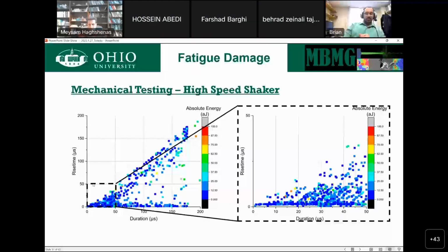And that means all of those waves for a fracture type event should exist down in this low rise time, low duration area. As you move away from that, you can start to introduce other mechanisms: more of a growth response, a longer crack increment, potentially fretting, anything else that might be producing an acoustic signal. What you'll find when you monitor this is that all of these early ones actually have a decent amount of energy, and most of them happen at the beginning of the loading, whether it's a monotonic or a fatigue test, particularly a low cycle fatigue test.